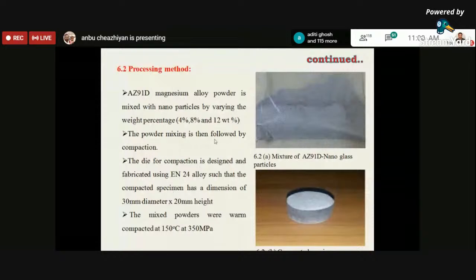So then the metal is compacted. The die for compaction is designed, and the EN24 alloy is used as the die. The die for compaction is designed and fabricated using EN24, such that the compacted specimen has dimensions of 30 diameter and 20 height. Okay, so it is subjected to warm compacting.